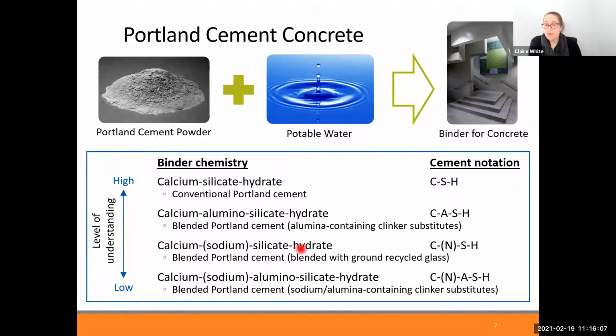Recently, people are now wanting to put ground recycled glass into concrete, which has a high sodium content often. So how does sodium affect the gel properties? And then even more so now, sodium plus aluminium in addition to the calcium silicate hydrate. So we have quite a good understanding of what's going on with the base calcium silicate hydrate gel. But as we are changing the chemistry of Portland cement concrete, we're also changing the chemistry of the gel itself. And we have relatively low understanding of how, say, sodium impacts the stability of Portland cement concrete.